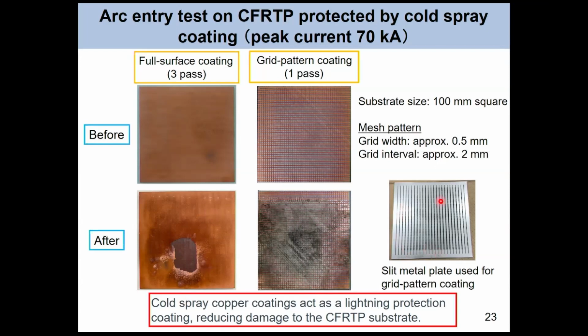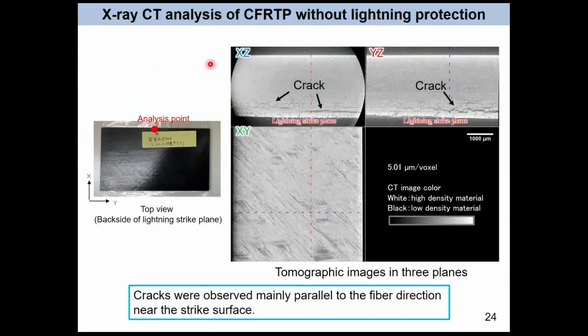This is a slit metal plate we used for making this grid pattern coating. And we performed X-ray CT analysis of CFRTP to estimate damage inside the CFRTP.